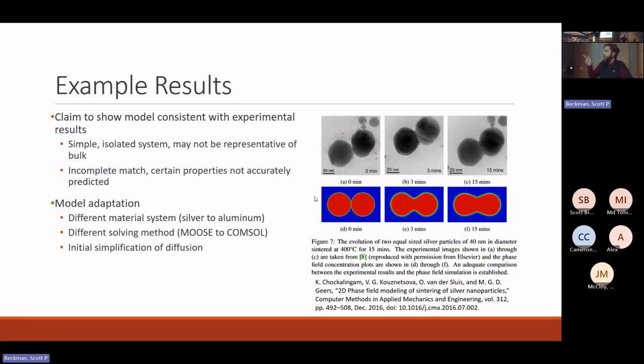In the paper that this model was mainly shown in, this was what they found. Basically, it showed the necking and growth between two particles in their system, relatively consistent with an experimental result they drew from a previous study. However, their model was extremely simple.